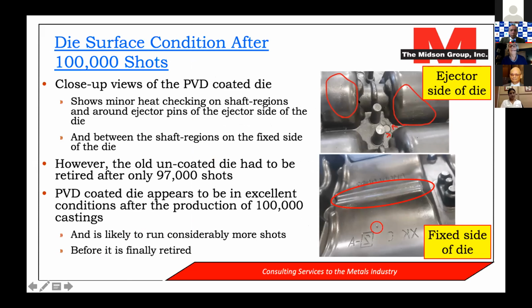And the areas that we have circled in red or with red arrows are showing some of the areas. So if you look at the ejector side, there is some minor heat checking on the shaft region, on the circular regions, and around the ejector pin area. And then on the fixed side, there's a little bit of heat checking damage here, and then between the shaft regions of the die. But again, this die has run 100,000 shots.